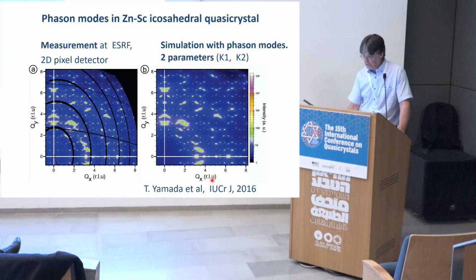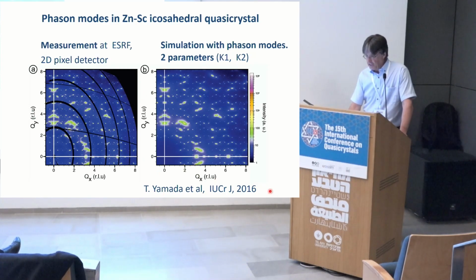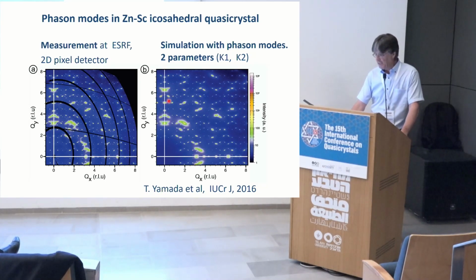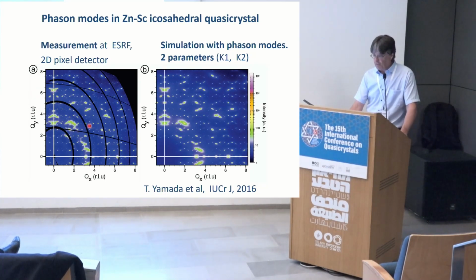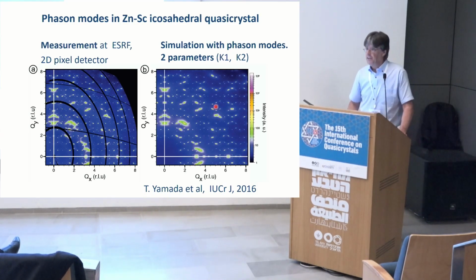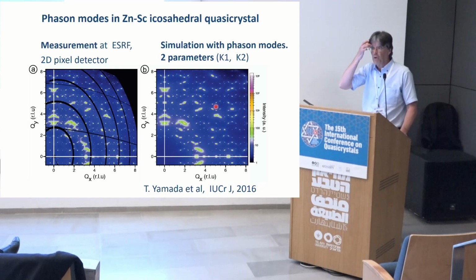It's a more recent result on the zinc scandium. This is using now this large two-dimensional detector. You have a whole overview of reciprocal space. You see a lot of diffuse scattering all over here beside the Bragg peaks, and that is what is reproduced. In the work done by Tsunetomo Yamada, you clearly see that the diffuse scattering is very well reproduced, which is a clear indication that we have these phason modes present in those structures.